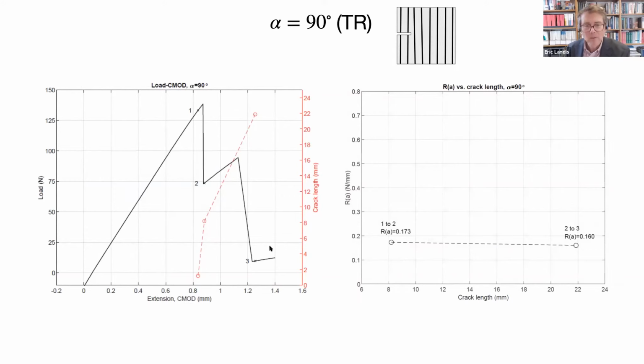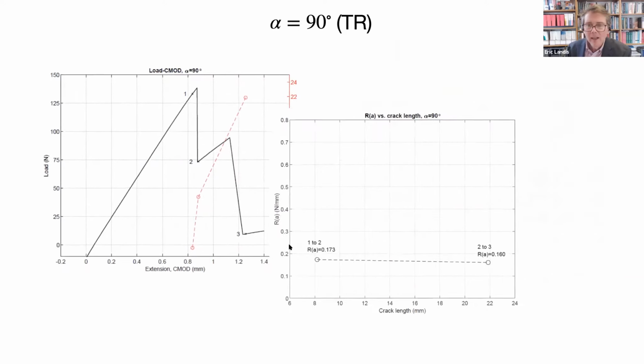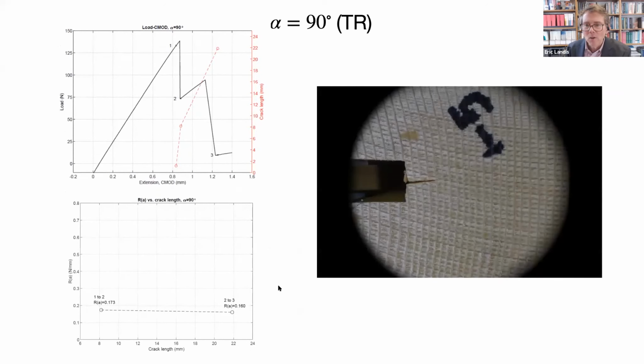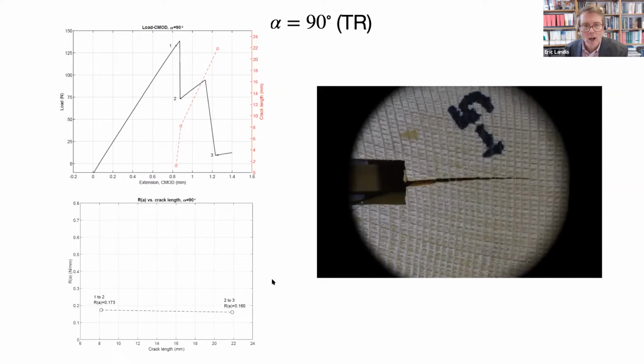And then finally, if we go to 90 degrees, now this is what's referred to as TR again. Now it's definite sections of unstable crack growth. And if we look at the images of the crack growth, again, the saw artifacts might be showing up here, but the grain of the wood is vertical here, and the crack simply propagates straight across with very little resistance, and basically no toughening.